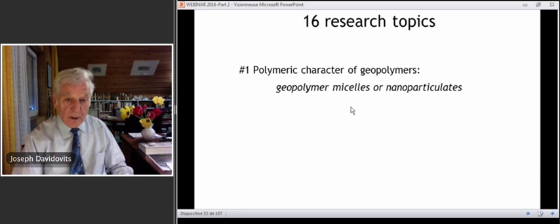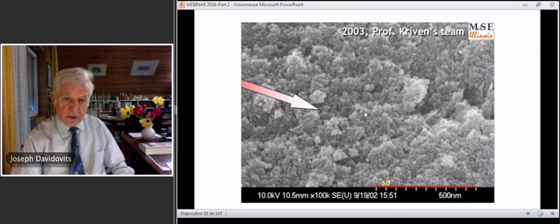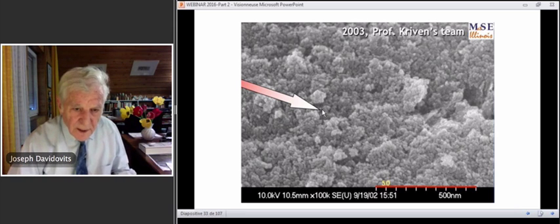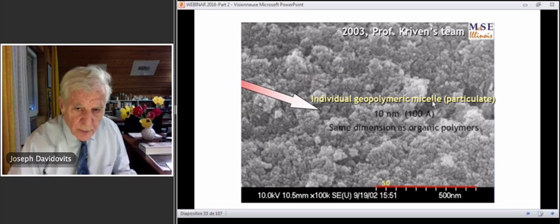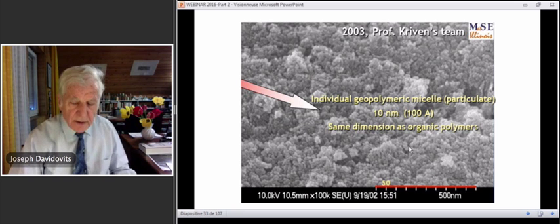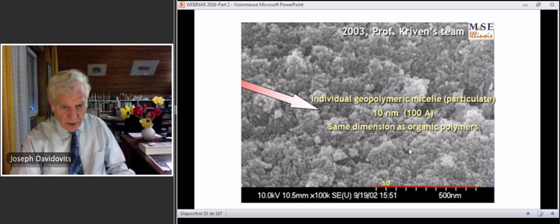First, polymeric character of geopolymer. We have polymers that have a very precise structure, and we call them geopolymer micelle or nanoparticulates, and they have been first shown by my friend Professor Waltraud Kriven at Illinois University in Urbana-Champaign. And you see here at the end of the arrow you have a small nanoparticulate. These are individual geopolymeric micelle particulates that are 10 nanometers in dimension, 100 angstroms. They have the same dimension as regular organic polymers.